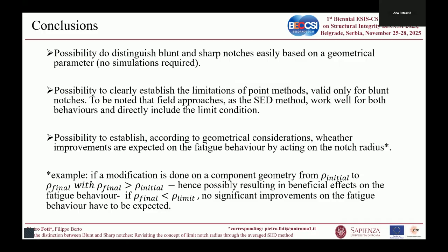Furthermore, by introducing this limit condition for the notch radius, it is also possible to establish, if we are going to design something and we want to improve its fatigue properties, whether a change in the notch radius will be effective in improving the fatigue properties. Because if we are in the sharp notch behavior and, by changing the notch radius, we are still in that behavior, we will not see an improvement in the fatigue behavior.